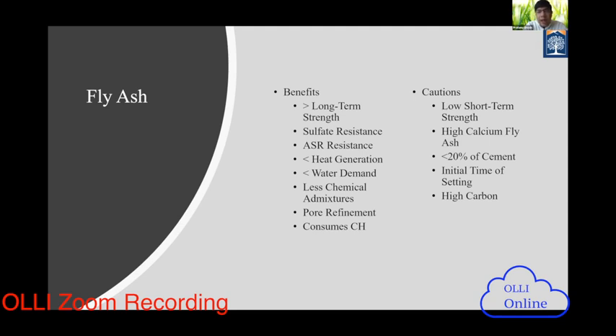Then what are the other challenges? Sometimes some of the fly ash has high calcium. When you have too much high calcium, especially class C, then the challenge is the purpose. We are using pozzolans, but if you start to have really high calcium, that goes more towards cement. It is becoming almost like a cement, not too much benefit. We have to use a heavy level of replacement. That's one of the challenges, with some of the fly ash, especially class C.